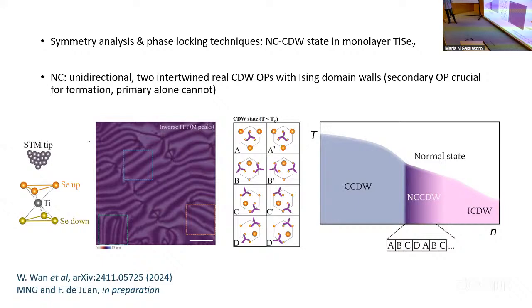And in this particular case, the way of developing this new order, which is basically charge modulations, has 8 possibilities. They are all the same. And typically what happens is that you lower the temperature and the system chooses one of them, and that's it. And this is what has been measured until now. You lower the temperature, you have this long-range order of one of the states. The system picks.